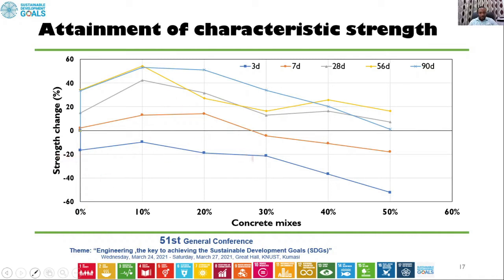Now this blue line is the 3 days curing period, and all the concrete mixes were lower than the characteristic strength. At 7 days, it was only the 10 and 20% that were higher than the characteristic strength. 30% was marginally lower than the characteristic strength. The 40 and 50% concrete mixes were all lower than the characteristic strength. However, at 28, 56 and 90 days, they were all higher than the characteristic strength.